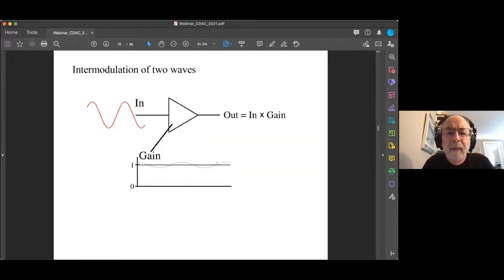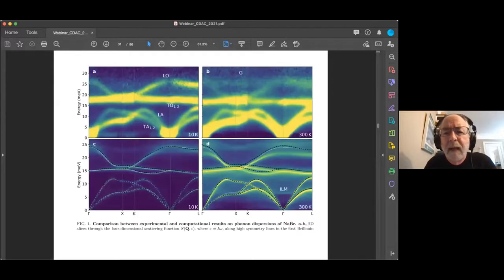And we noticed that the energy here is the sum of the energy of this broadband and that broadband. They sum up to be about, 7 and 17 is about 24 or something like that. And the difference between them is about this intrinsic localized mode energy, which is down here, it was supposed to be around 8 or something like that. Well, I haven't measured things right, but this is also a little hard to know exactly where that is.